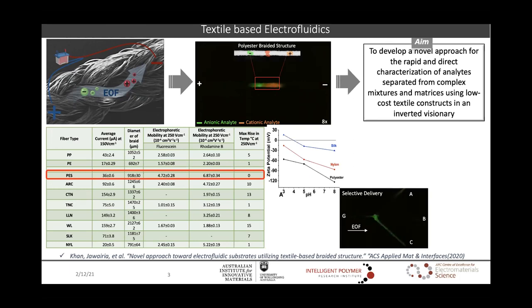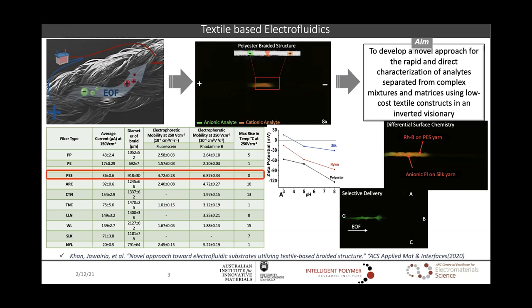Moreover, the braiding technique, which was used for the fabrication of 3D textile constructs, being simple and versatile, also offered the potential for selective migration of solutes to targeted different channels. Further, we demonstrated the versatility of the system and showed how composite braid matrix yarns of differential surface chemistries revealed a unique behavior of separation and parallel movement of oppositely charged solutes.